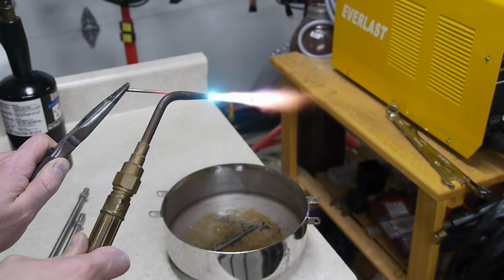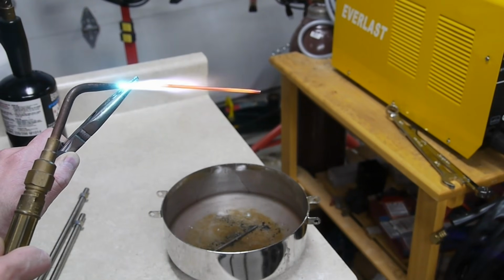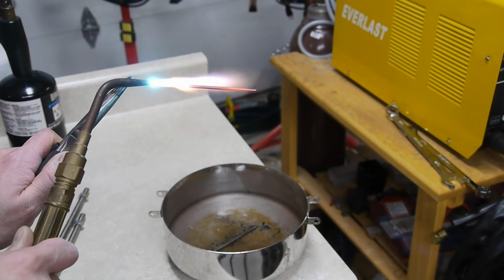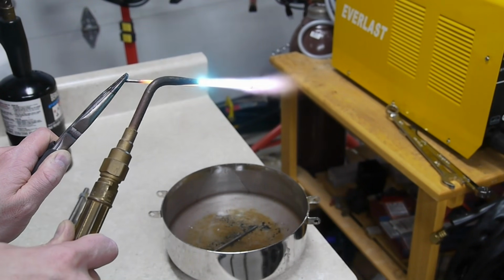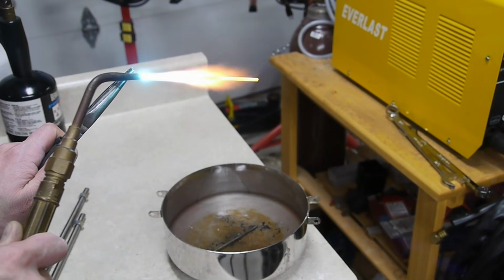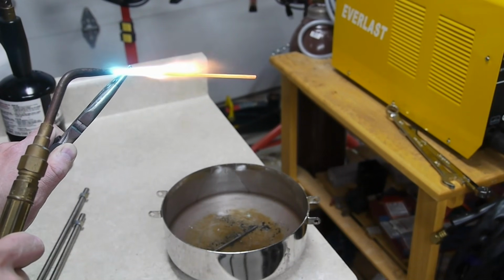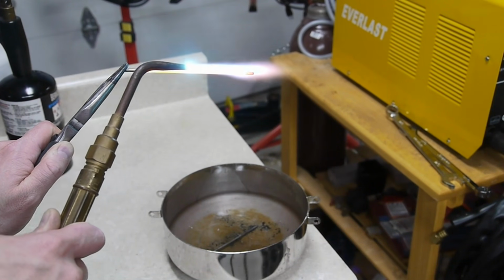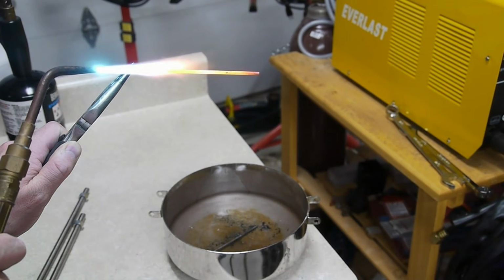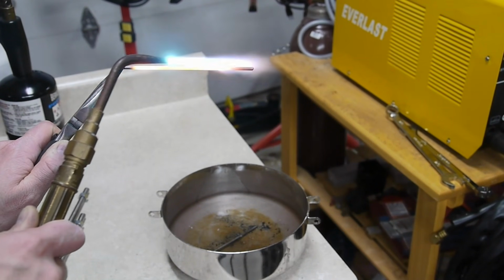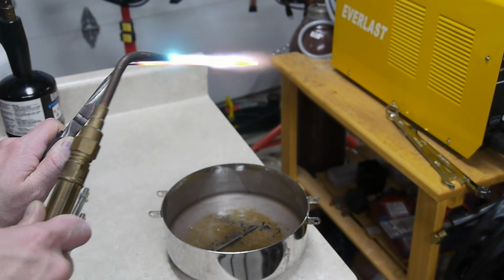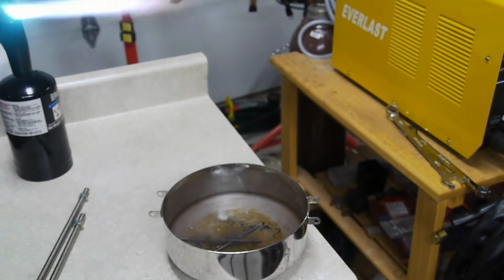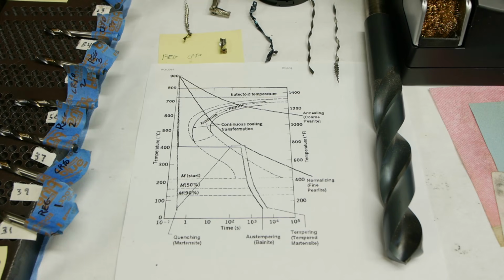Recall that when you want to harden a piece of steel, provided it has enough carbon content, about over 0.4 or 0.5%, the way you do it is heat up the piece of steel to red heat and then quickly quench it. And rapidly cooling it is what causes this crystalline structure to form that's really hard. It's not very tough, it's actually very brittle, but it is very hard. And I have a whole video on steel hardening if you're interested in that.